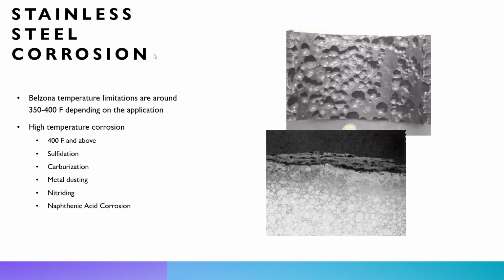So going into corrosion of stainless steel, there's definitely a lot of high temperature corrosion cases, in the 400 to 1000 F range. Just to let you know, Belzona temperature limitations are around 350 to 400 F. So if you're having some of these issues that typically occur above 400, somewhere in the 700 to 900 F range, Belzona might not be the alternative in that scenario. This is definitely big issues within the industry, and some of the ways you fix this is upgrading your metallurgy to super duplex or something even better than your standard stainless steel applications.